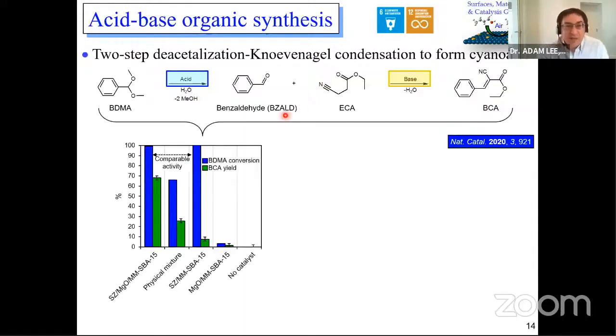So if we look first of all at the reactivity of our catalyst for step 1, again looking at a conventional catalyst. So this catalyst here is a pure acid catalyst. What you find is that our spatially orthogonal catalyst that has acid and base sites performs very well for the first step. So this is a pure acid catalyst. This is our spatially orthogonal acid-base. The two essentially are identical for conversion of this molecule here. However, and in fact, if you look at the final product over here, the yields of BCA are very poor when you use an acid catalyst alone.